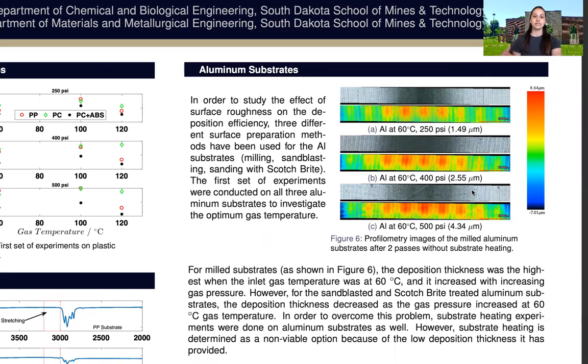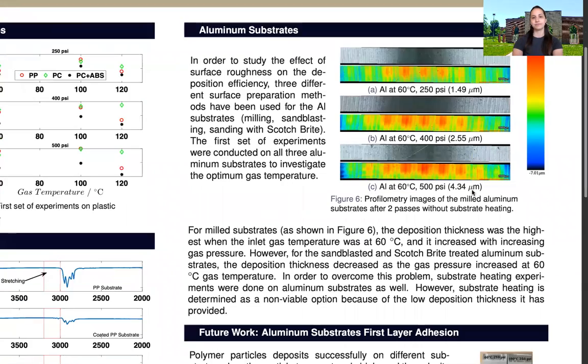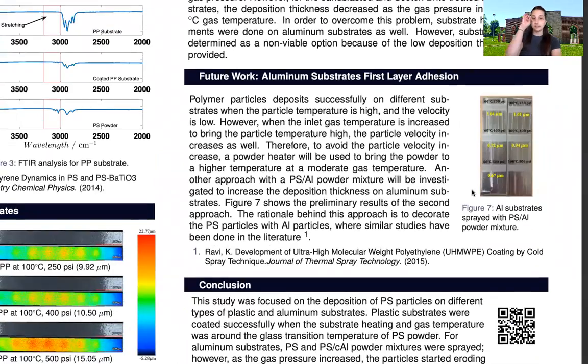However, for the other substrates, the deposition thickness decreased as the gas pressure increased, indicating weak particle adhesion in the first layer. Still, we cannot conclude, but we should investigate the bonding mechanism of the particles to come to a conclusion. For future work, since the polymer particles successfully deposit on different substrates when the particle temperature is high and velocity is low, we decided to use a powder heater.